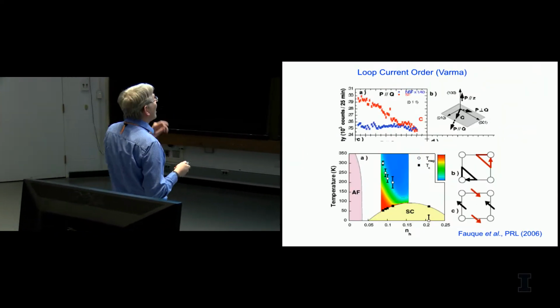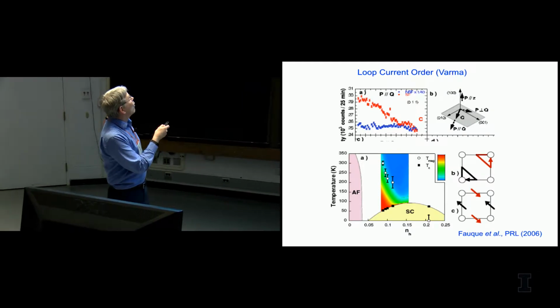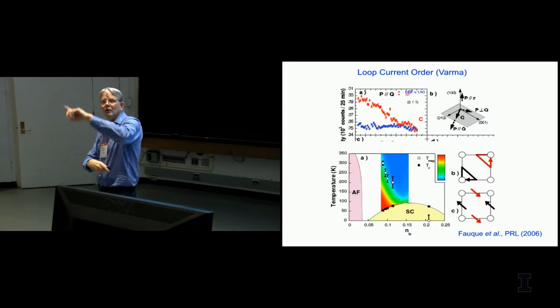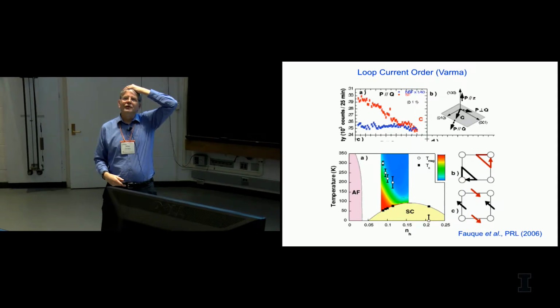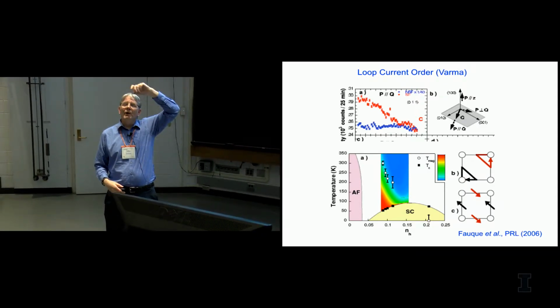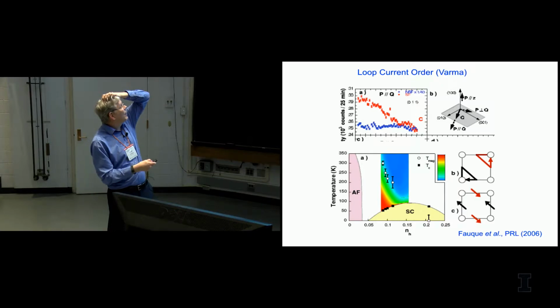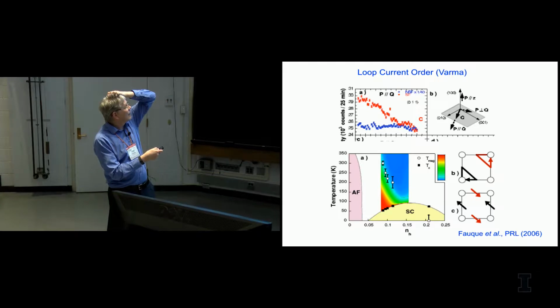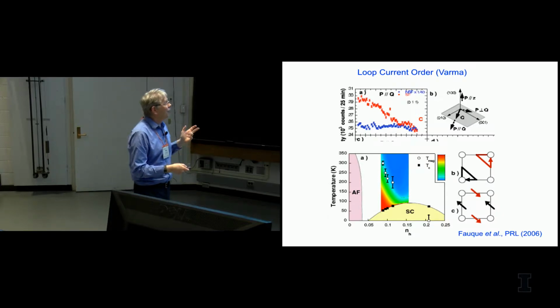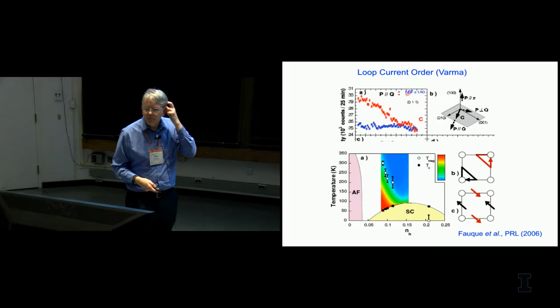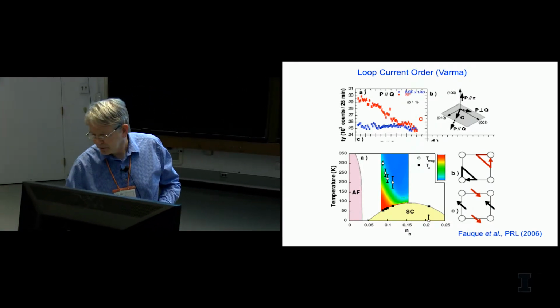Evidence also was seen for time reversal symmetry breaking. This was an early proposal by Chandra Varma that you would have basically loop currents existing in the sample where the hopping matrix element would be complex, which would lead to time reversal breaking. There was a prediction by this, which was later seen by neutron scattering, and that signal more or less cuts on at the same so-called T star. And one way of interpreting this is that you had these loop currents like this, which were anti-phase from this copper site to the next, although there are potential alternate explanations involving magnetism on the oxygen sites as well.